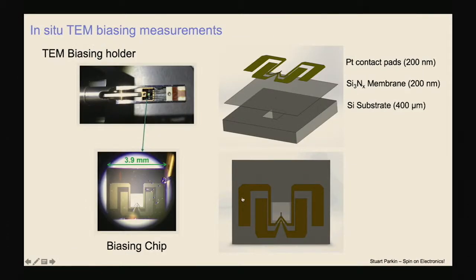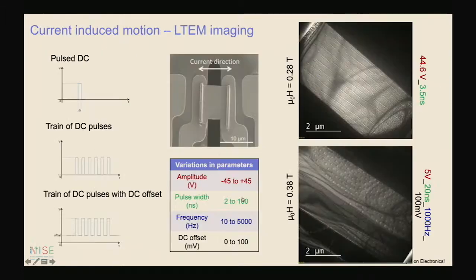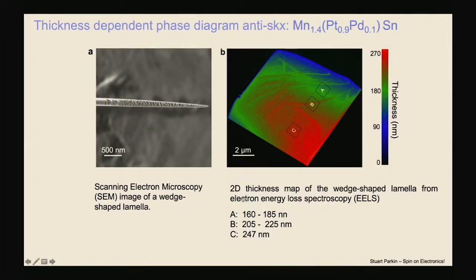Now, I want to briefly mention, to look at these structures, we make from a single crystal, we cut a layer which can vary in thickness from 50 nanometers up to several microns. And we've been exploring the current-induced motion of these antiskyrmions. I'm going to skip that because we're running out of time.